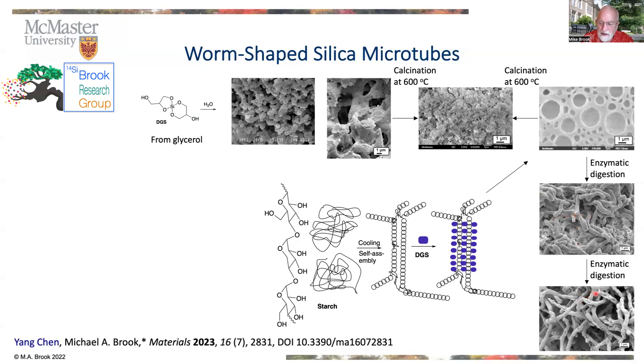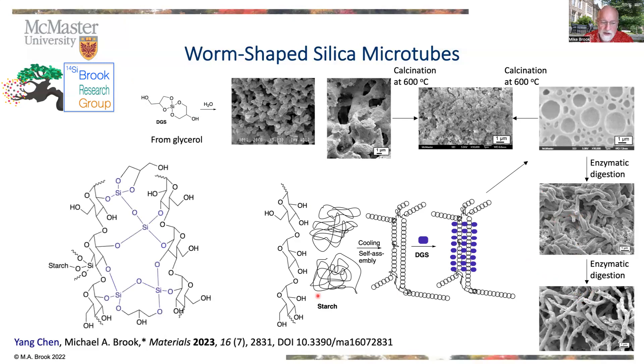After the second digestion, you can see that they're actually hollow on the inside. What we think is arising from this is a true templating effect. The DGS does chemistry on the surface of the starch, but it actually becomes an alkoxy silane. That material, which is something between bio-organic and inorganic, is not digestible by the enzyme. And so we see the worm castings that are shown in the picture.